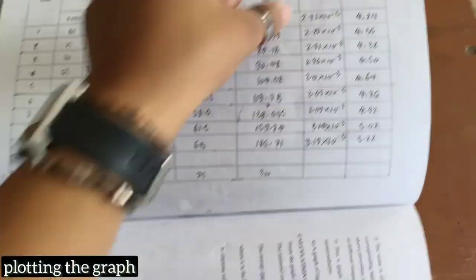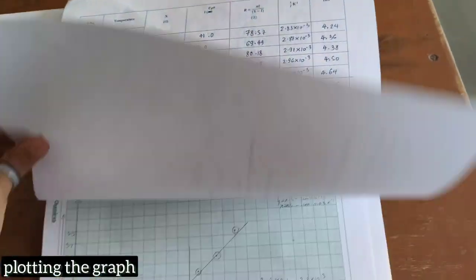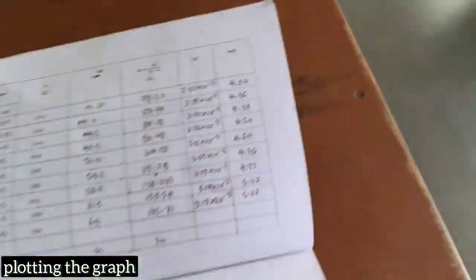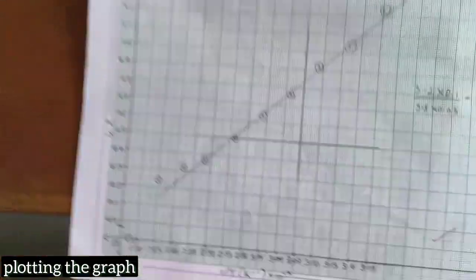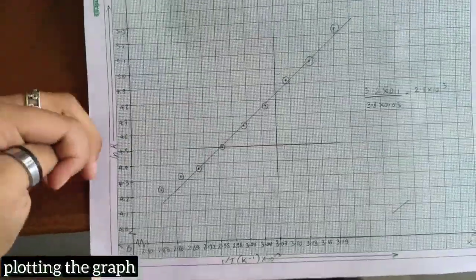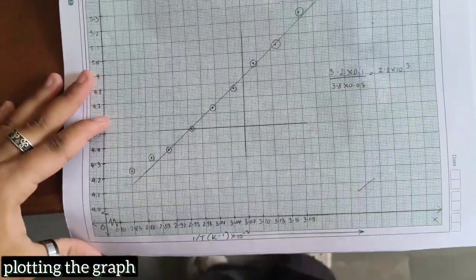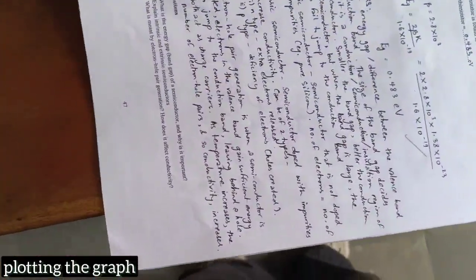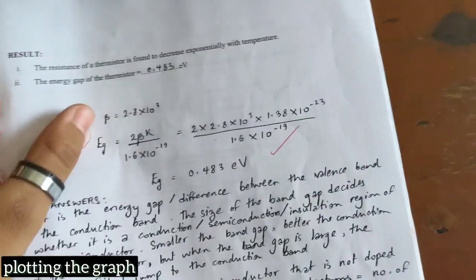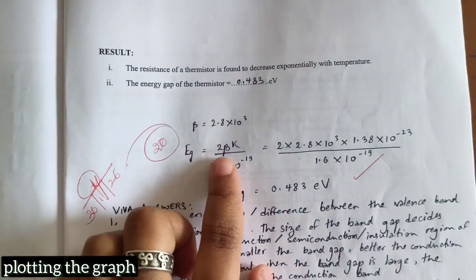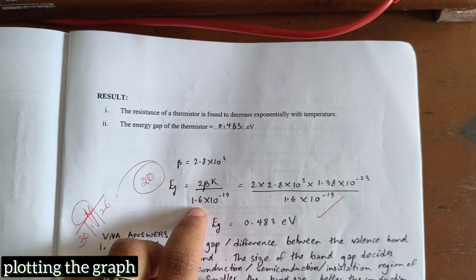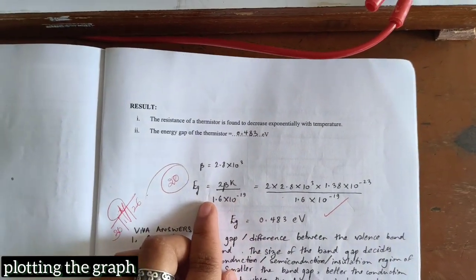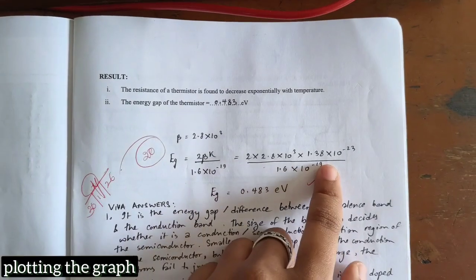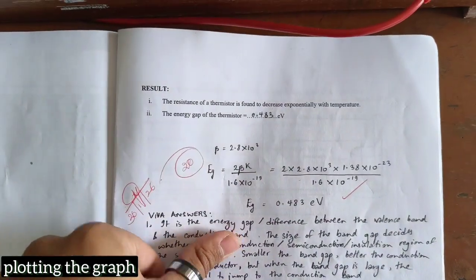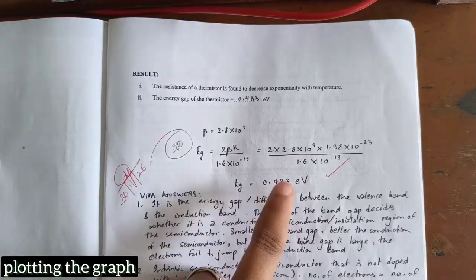And for the graph, you have to plot 1 by T on the x-axis, like this, and on the y-axis you'll be plotting the log of R, which is the last column, and you're expecting to get a straight line graph. Basically you have to calculate the slope of this graph, and that slope is this beta that you have here. Then you can find the energy gap using the formula 2 beta k by 1.6 into 10 power minus 19. This is the charge of an electron, and k is basically Boltzmann's constant. So then you can find the energy gap using this formula.